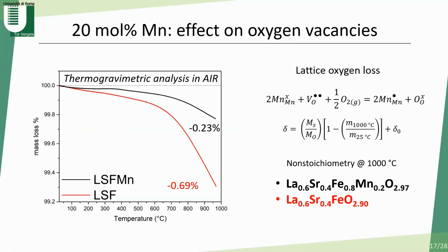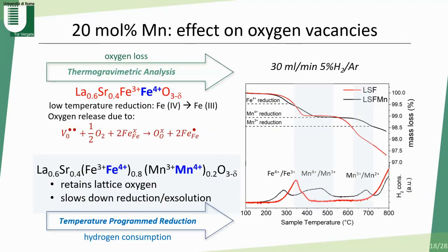First of all, we investigate the effect on oxygen vacancies, and here it is clear that by increasing temperature, the oxygen released in manganese-substituted LSF is much lower than the reference compound. This is true also in reducing conditions. In this figure, I reported the TG in hydrogen, and in the same temperature range, also the temperature programmed reduction measurement, where each peak corresponds to the hydrogen consumed for the reduction of cations. As we can see, again, the overall effect of manganese is to retain lattice oxygen, slowing down the reduction and exsolution.